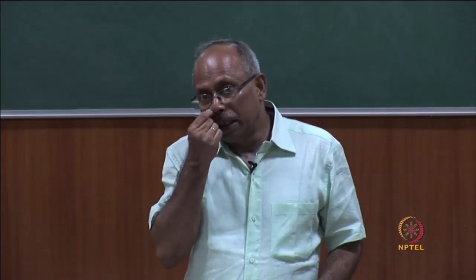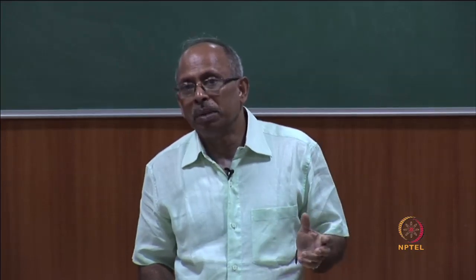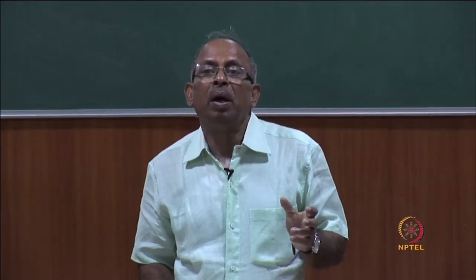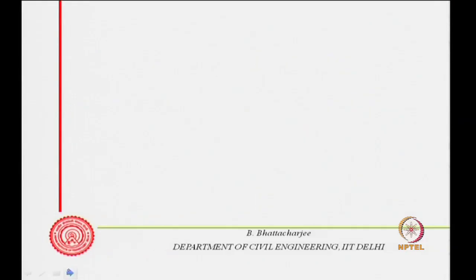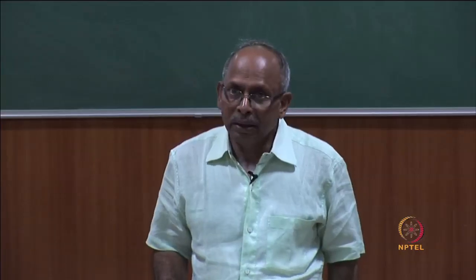All right. So, the ultimate creep coefficient can be related to the creep coefficient at any age, with a similar kind of formula and the same basic concept, and then it can be related to the creep function as we have done in the last lecture. You can predict by using either method, but with modern-day Excel sheets, it is fairly easy to use the factors k1, k2, k3, etcetera, and simply multiply them by 2.35 to find the ultimate creep coefficient, which can finally be related to the creep function in a similar manner as we did in the last class.